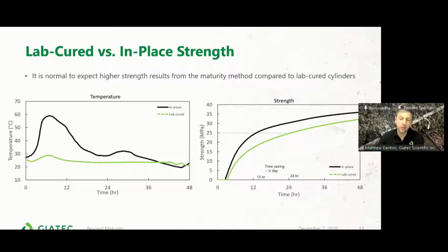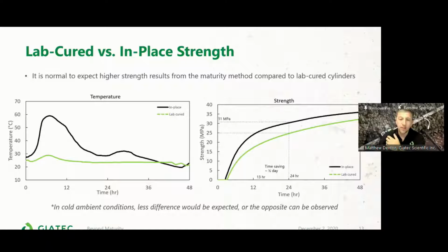So what does this result in? This results in a very different temperature and strength gain in our in-place concrete. Here in the black line, we can see on this graph on the right that our early age strength spikes a lot quicker. It does plateau out towards the end, compared to the strength that we gained from the cube sample. So if we look at that in the scenario where we're worried about 31 MPa, we're trying to reach a target strength, as you can see here, at 24 hours we're reaching 31 MPa on our in-place concrete. So that's the in-situ concrete.